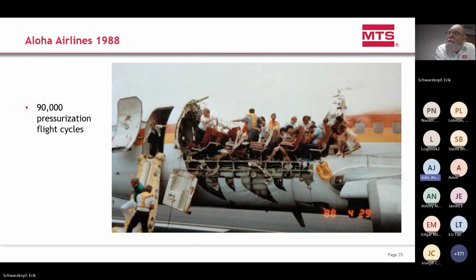We still have problems with decompression, with explosive decompression. This is from an Aloha Airlines flight in 1988. In Hawaii, the flights are relatively short—20 to 30 minutes is probably the longest flight between the islands. In this case, it wasn't a design failure, it was more of a maintenance failure; there was poor maintenance done on a repair on this one. But the idea is that this flight landed, and everybody on board lived except for the flight attendant who was not buckled in at the time. The idea is that explosive decompression happens rarely, but it still happens.